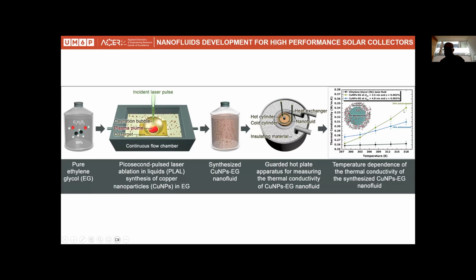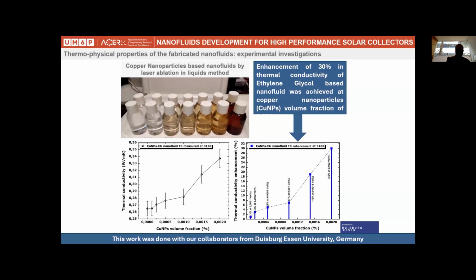What I'm showing you here is the difference between nanoparticle sizes. The blue one shows that if the nanoparticles are bigger, the achieved enhancement is around 18%, which means smaller nanoparticles give higher thermal conductivity enhancement. This is one of the reasons we selected pulsed laser ablation in liquid, because it allows us to produce nanoparticles below 10 nanometers. Here I am dealing with nanoparticles of around 2.5 nanometers that we managed to produce using our laser system.